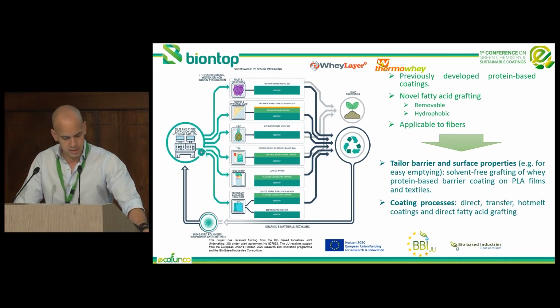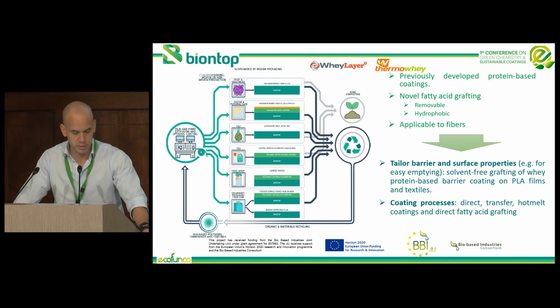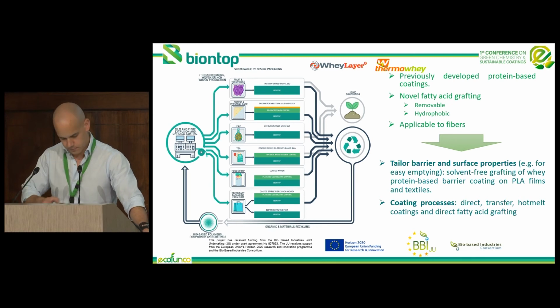Likewise, in the field of textile, most used coatings, like, for example, polyamide, polyurethane, are not bio-based and of different nature than the fibers that they are applied on, limiting the properties of the recycled materials. And here, PLA, or BIOnTOP copolymers, based on PLA-based coatings and fatty acid grafting have been developed, allowing reprocessing of the coated fibers without significant loss of properties. So in conclusion, our coatings are multifunctional, used for barrier, easy emptying, and sensory purposes.